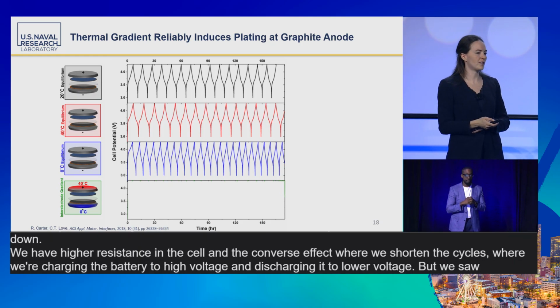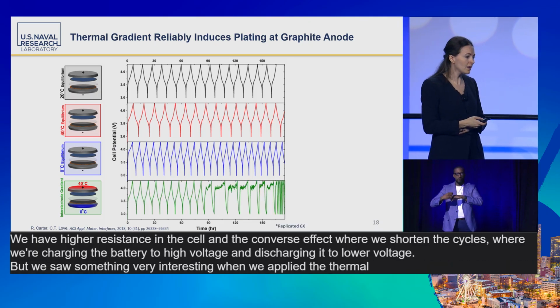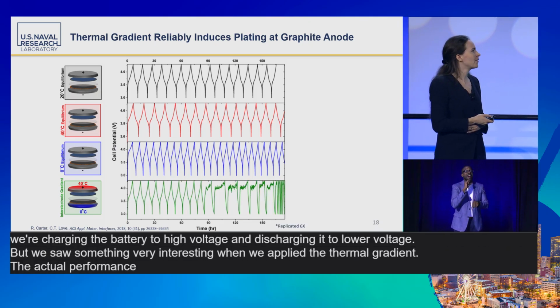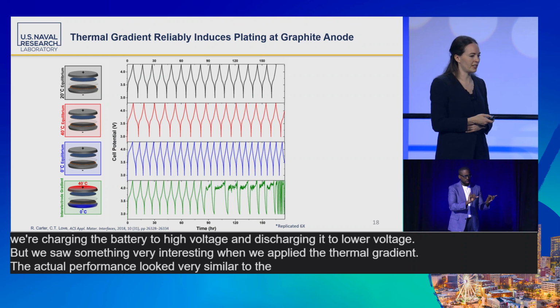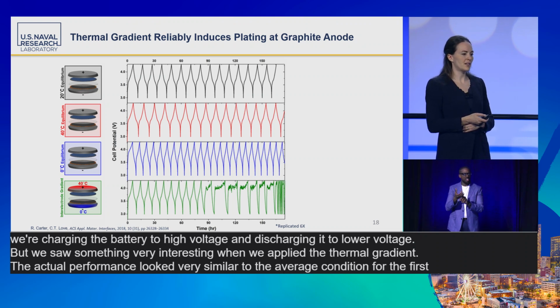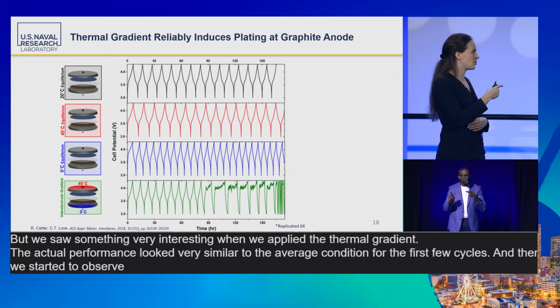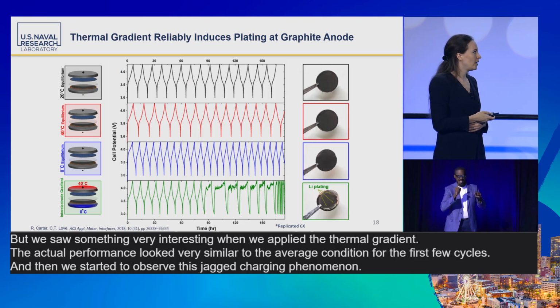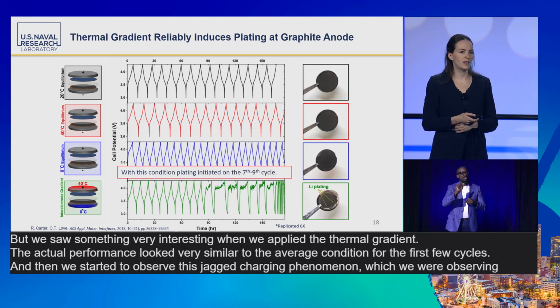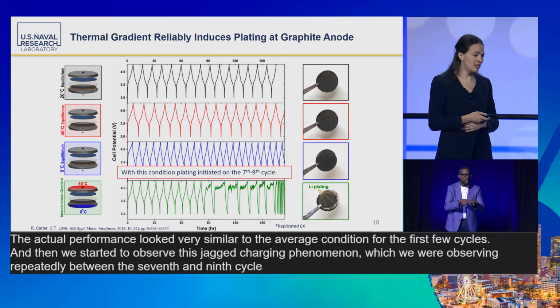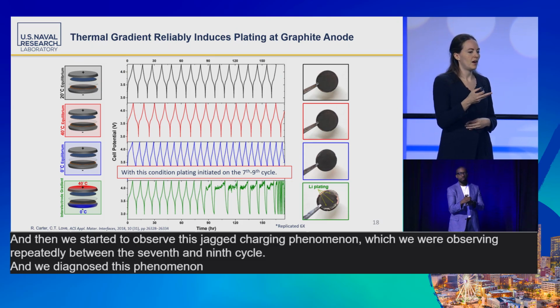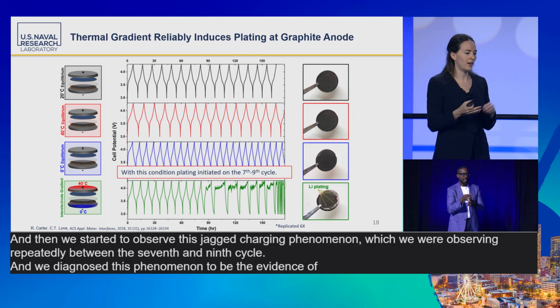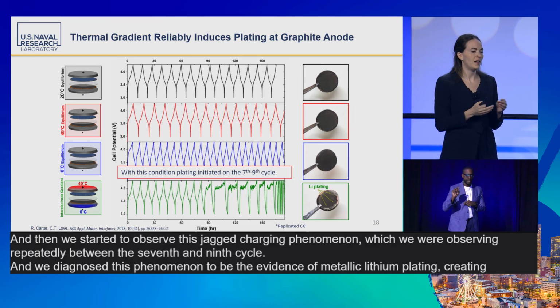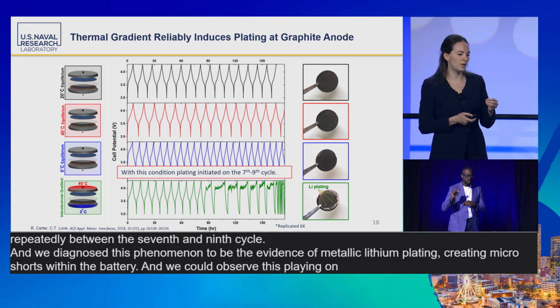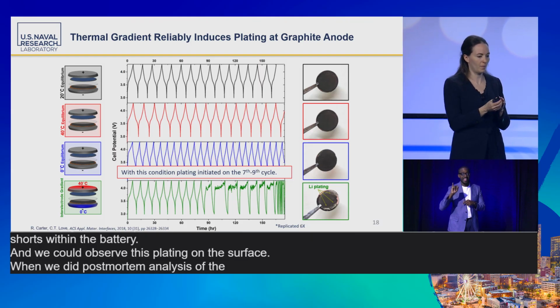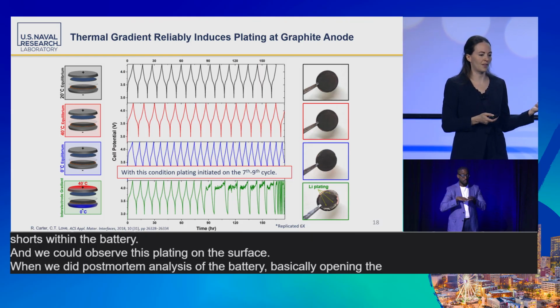But we saw something very interesting when we applied the thermal gradient. The actual performance looked very similar to the average condition for the first few cycles. And then we started to observe this jagged charging phenomenon, which we were observing repeatedly between the 7th and 9th cycle. And we diagnosed this phenomenon to be the evidence of metallic lithium plating creating micro shorts within the battery. And we could observe this plating on the surface when we did post-mortem analysis of the battery, basically opening the cells up and looking at their surfaces.